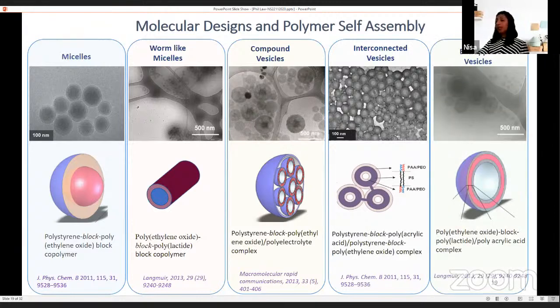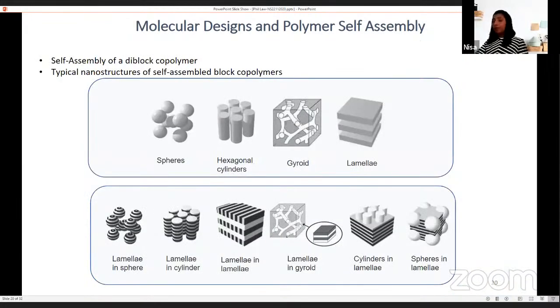Another morphology we developed is a vesicle called an entrapped vesicle. That is, you can see one vesicle is entrapped in another vesicle. We used various combinations of block polymers for the design of these nanostructures. These block polymers can also form these nanostructures in their solid state too. These are the major nanostructures they form in their solid state. In addition to this, they can also form hierarchical structures such as sphere in lamellae, lamellae in lamellae, etc.